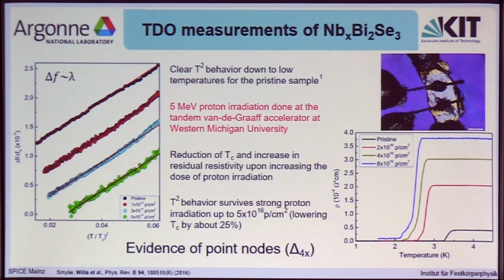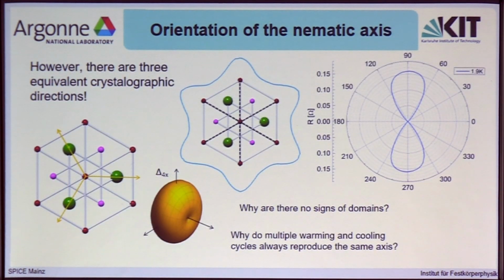Okay, having excluded conventional sources and thinking we know that this type of gap structure is realized in our systems, there's one thing which is puzzling for everybody working in this field so far, and that is the fact that in almost all measurements, there's no observation of domains. Why would you expect domains? Well, we have a trigonal system, so it has three equivalent axes. If this twofold gap structure has a preferred orientation, it should still pick one of the three axes at random.